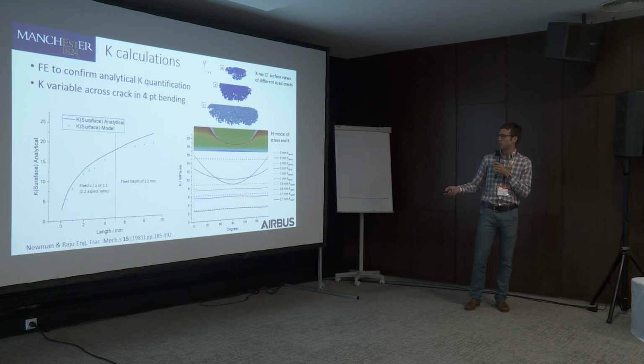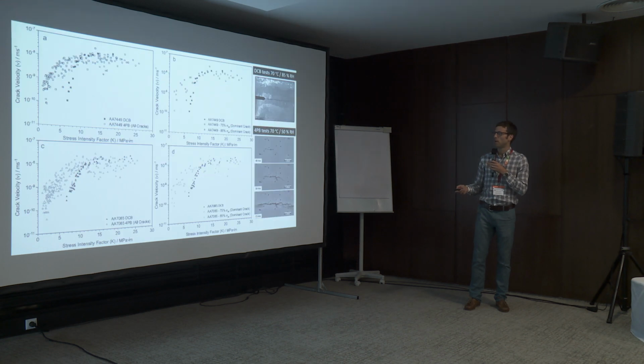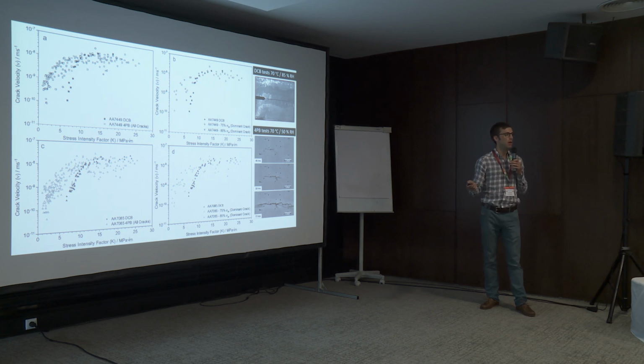And you can see here, as the crack grows, we see a big difference in the K that we get at the top surface where we're making our measurements and in the depth of the sample. But we're confident now that we can create these crack velocity versus stress intensity factor, V-K, plots. And what we're showing on the top is the 7449 data and the 7085 at the bottom. And we've plotted it against the open symbols, which are the results from this 4-point bend test, compared to a more traditional DCB measurement, where we have a double cantilever beam test and a large crack.